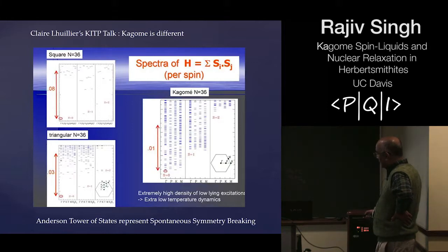The energy scale is reduced, but you can see the spin 0, the 2 spin 1 and the 3 spin 2 states are separated from the other states basically in each sector. And now because we have a 3 sublattice structure, it turns out again this theory of spontaneous symmetry breaking will tell you exactly what the count and what the momentum of those states are going to be, and it will be the linear superposition of these that will give us long range order. So we believe a pure triangular lattice Heisenberg model actually develops long range order. But if you look now at the spectrum of the Kagome lattice, it looks very different. On this scale, which is a much lower energy scale, you have first of all a huge number of spectrum, and furthermore what you see is within the singlet there are massively large number of states below the lowest triplet state. So below the lowest triplet there is a very large number of singlet states. So somehow the singlet states are dominating. The physics has no relationship to this spontaneous symmetry breaking, which leads to antiferromagnetic order.